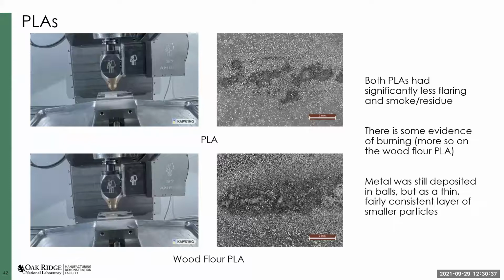And we also got more of an embedding of the feedstock powder than melting and resolidification as a bead, which was very interesting. So it doesn't really provide that same ablative effect of exposing something that could protect the bulk polymer. So this was less promising as a feedstock material.